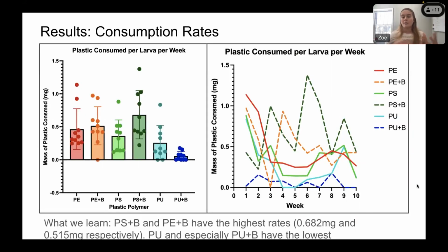So getting into my results, as you can see in these consumption rates, the polystyrene bran and the polyethylene bran had the highest average rates with 0.682 milligrams per week per larva for the polystyrene bran and 0.515 milligrams per larva per week for the polyethylene bran. As you can also see in both graphs, the polyurethane containing groups did not eat nearly as much as the others. And so for the interest of time in this presentation, I'm going to focus on polystyrene and on polyethylene.